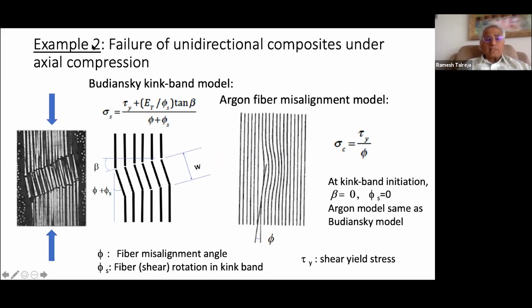Okay, I'm going to shift gear and go to another example, which is very different, but illustrates the concepts of this particular strategy. So we are looking at a unidirectional composite under axial compression. And at some point, what happens is that you form a kink band. This is now a classical result. Everybody knows about it. This is what happens. At some point, the fibers break along a certain direction or along a plane, and another set of fibers fail in a parallel plane. So between those two is what you say a kink band has formed, because it's a kink here. And between those two planes, the fibers then undergo rotation.